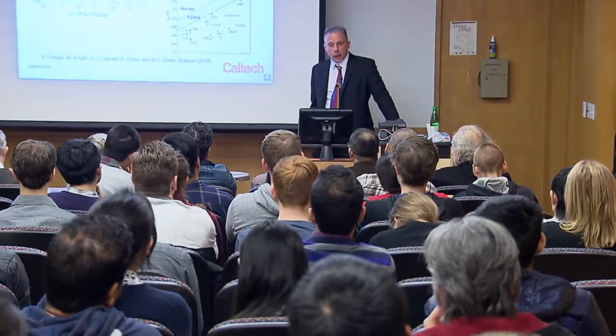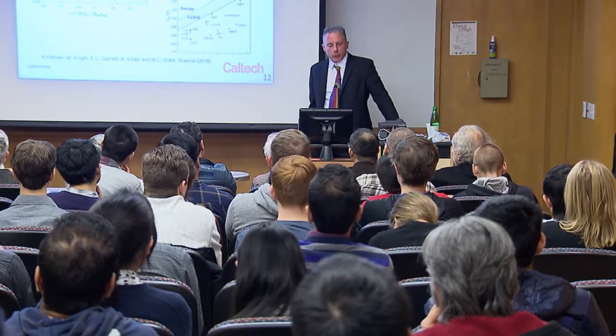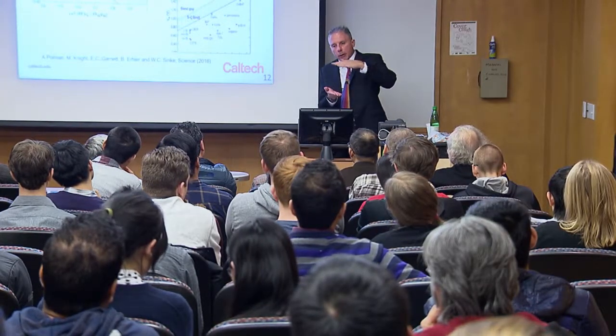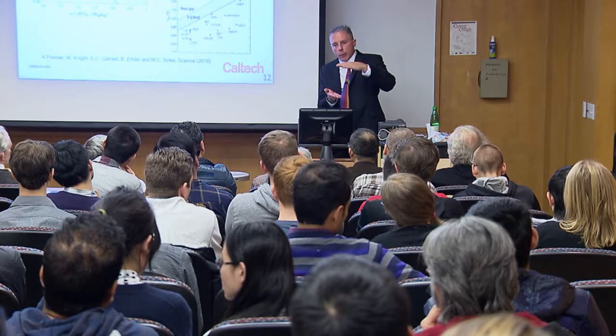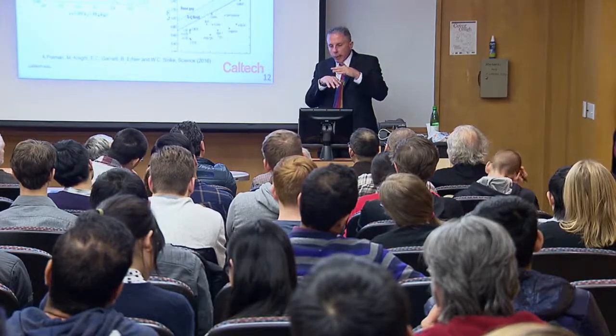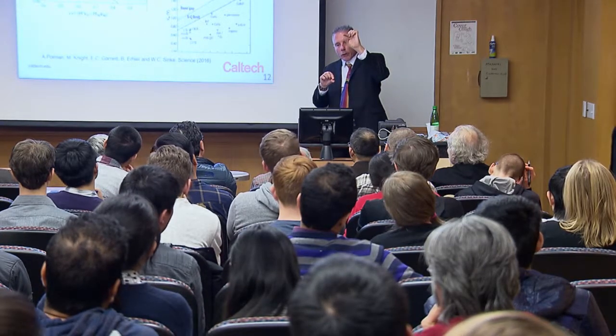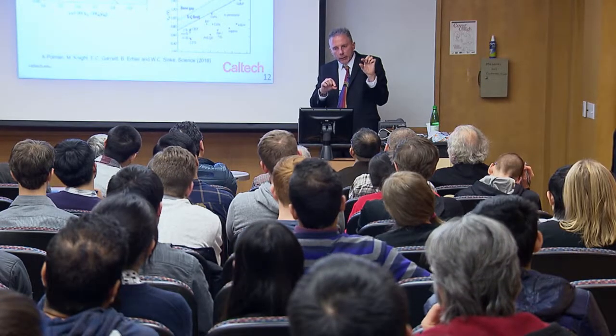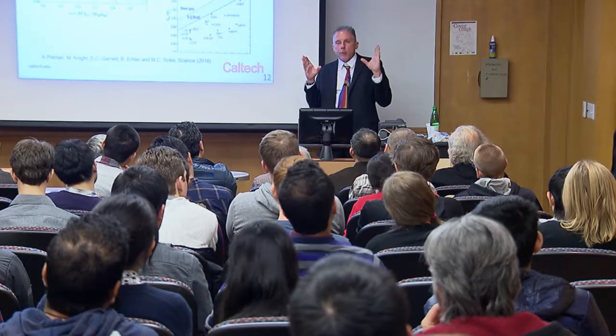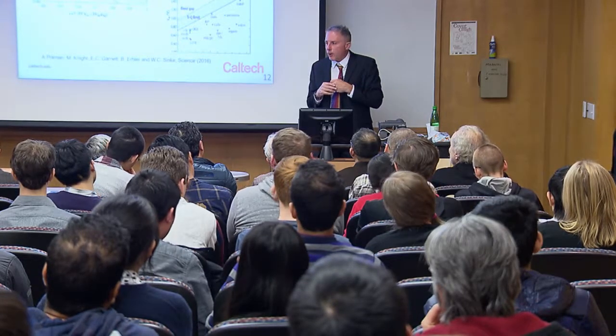Sometimes you have to accept the gifts that nature gives you, which it did with gallium arsenide, and which it has done with the perovskites. These are materials that have remarkable properties. From a semiconductor physics point of view, the thing you want to avoid is electronic defects that lie within the center of the band gap. Those defects tend to be non-radiative and drive very high rates of non-radiative recombination. The perovskites, for example, are incredibly disordered materials—practically liquid-like in their structure. But remarkably, the defect states are all concentrated near the band edges. There's a remarkable lack of defects in the center of the band gap, so it can support very high radiative and low non-radiative recombination. So from a materials design point of view, that would be one of the most important criteria: try to design things that don't produce a lot of defects right in the middle of the band gap.